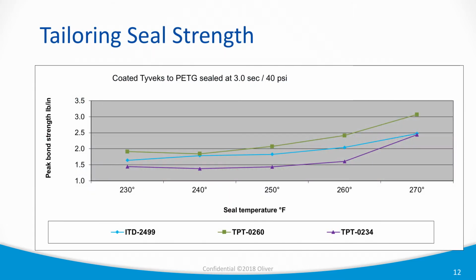This on the left side is the peak bond strength in pounds per inch, and we have the seal temperature on the x-axis, and the top line there is the standard product, the TPT 0260, the green line. The bottom line was the so-called soft peel, the 0234, that's the purple, and we formulated to go right in the middle. And they were happy with it, and it met all their requirements, and they went forward with it.